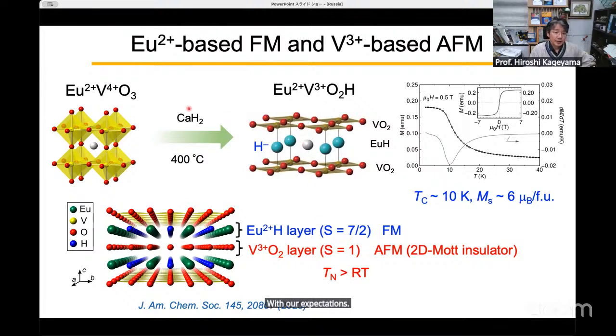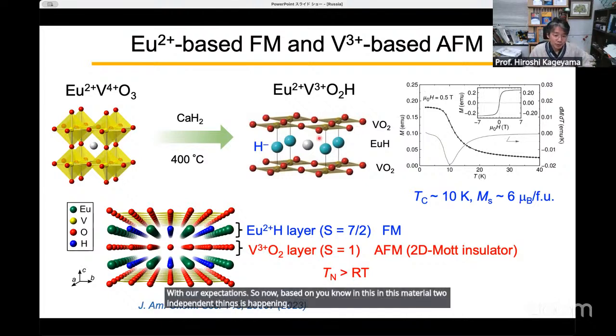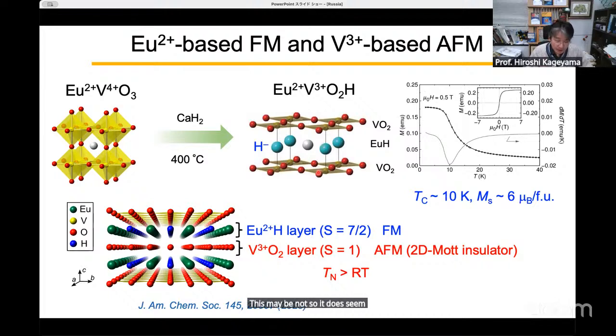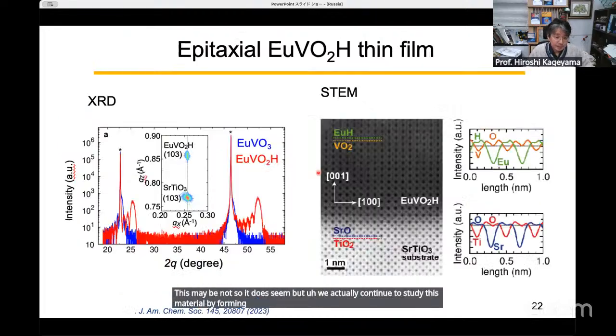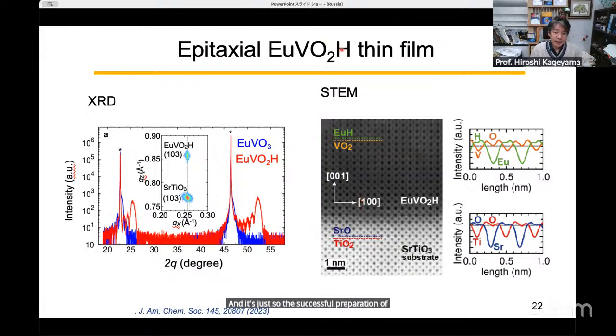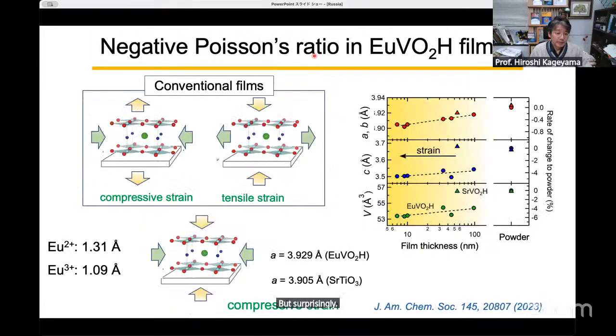So in this material, two independent things are happening. This may not be so interesting, but we continued to study this material by growing epitaxial thin films using the STO substrate. This just shows the successful preparation of these epitaxial thin films. But surprisingly, we obtained a very interesting change in lattice parameters. Here, I show the film thickness dependence of the lattice parameters.